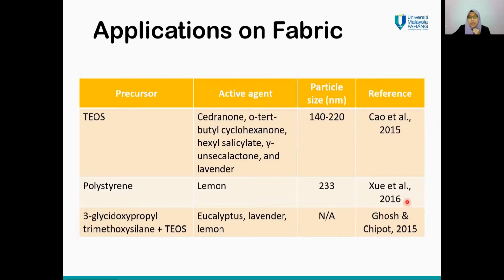Meanwhile, Xue et al. in 2016 fabricated hollow mesoporous silica nanospheres via sol gel method with a size of 233 nanometers using polystyrene template and loaded lemon essential oil with a loading capacity of 85.8%. The amount of lemon aroma released from dried nanocapsules was only 7.9% after 6 days at a temperature of 20 degrees Celsius. Furthermore, the aroma took more than 30 hours to be completely released at a high temperature of 50 degrees Celsius.